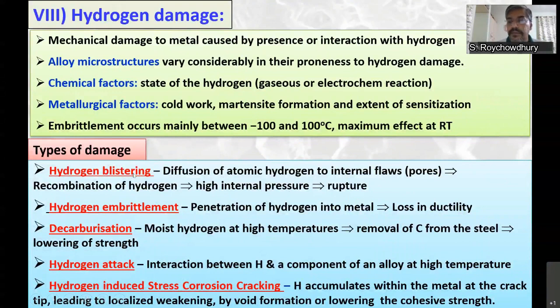So what are the different types of damage? Hydrogen blistering. Hydrogen blistering occurs if you have pores inside the metal. The atomic hydrogen will diffuse into those pores, and inside the pores it will recombine and form hydrogen molecule gas. Once the gas forms molecules, it cannot come out of those closed pores, and it will lead to high internal pressure that will lead to rupture of the steel, even though the external load is very, very low, because the internal pressure will add up to that external load.